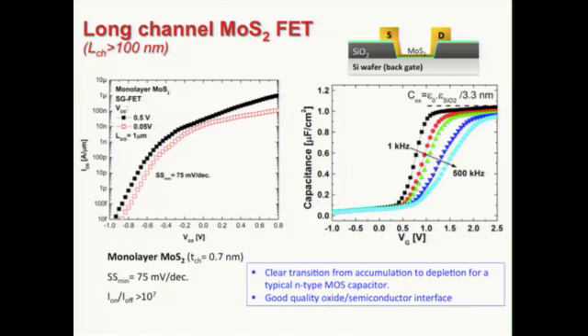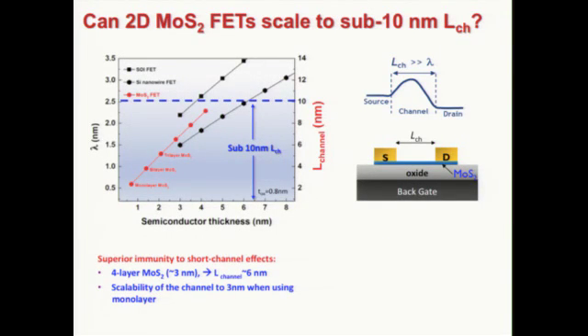But now the question is, can we really scale it down to sub-10 nanometer or not? This graph shows the minimum channel length of a transistor versus semiconductor thickness, benchmarking a silicon nanowire structure, which has the best electrostatics, this is the best silicon transistor we can build, and a planar molybdenum disulfide transistor. As you see, to have a channel length of about 6 nanometer, we need about 3 nanometer of silicon. So the diameter of the nanowire has to be about 3 nanometer, which, as I said, is really the physical limit. It's already beyond the limit of silicon.